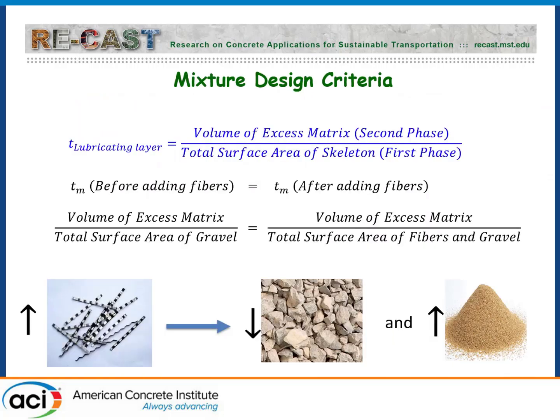So from a mixture proportioning point of view, you've probably read about this. When we design fiber reinforced concrete, you want to maintain the thickness of the mortar layer to be the same. So when you have fibers, the thickness of the mortar needs to be the volume of excess mortar divided by the surface area of the coarse aggregate, in this case gravel, plus fibers. By doing that, you can improve the workability of the concrete, which means when you add fibers, you have to reduce the coarse aggregate and slightly increase the sand content.